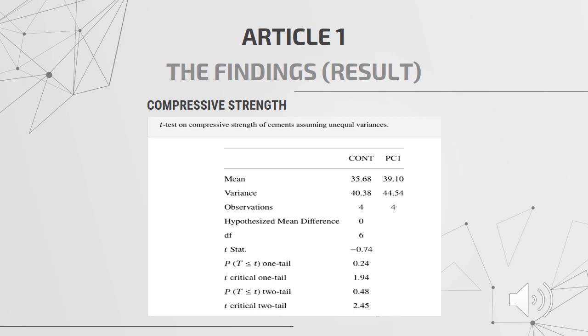This is the result for compressive strength. The test between the two cements shows that the strength achieved was statistically insignificant. This means that there is no significant difference in terms of strength at the standard curing periods. The use of green cement is very much suitable for any working place of Portland cement.